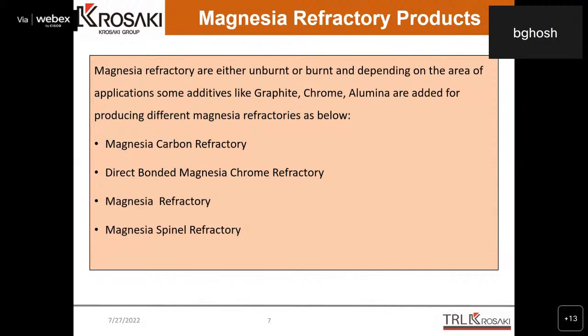Direct bonded magnesia chrome bricks, in combination with chrome, have magnesia direct bonding at ultra high temperature firing, 1750 to 1800 degrees centigrade. They are used in the non-ferrous sectors, in the copper, zinc, and lead industries, where various copper concentrates are produced from 60% purity level to 99% purity, where magnesia chrome offers excellent corrosion resistance towards the fayalitic slag produced in copper producing units and the zinc industry, ISA smelter, PS converter, all these areas. Apart from this, magnesia spinel and magnesia refractories are also used in the cement industry and electric arc furnace backup lining. So magnesia finds a host of applications as a utility.